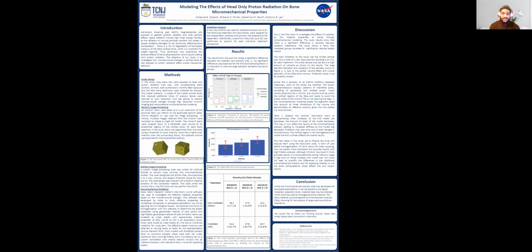The large variance is due to the variability of the tibia's unique microarchitecture, partial volume effects, small sample size, and RVE index detail reduction. The bone's microarchitecture displays unique patterns of interstitial pores. During the RVE generation in Mimics, it's imperative that the volume must be within the cortical regions of the tibia and avoid the empty spaces of the micro CT file or risk approximating the composite effective modulus to be only air.